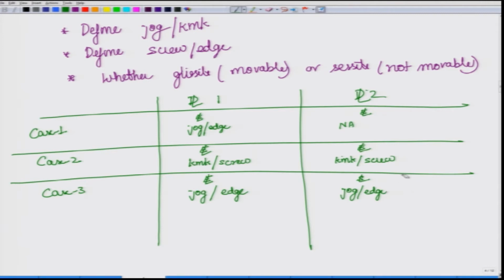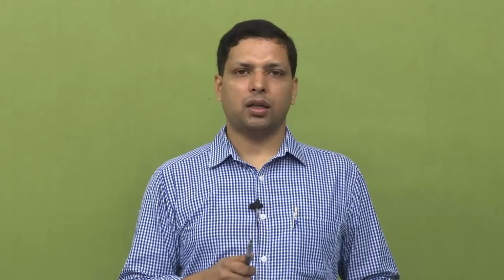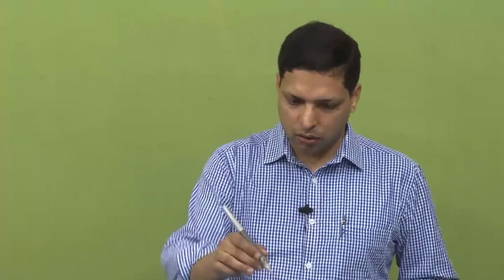So, I will put a star mark over here because this is to be remembered: it depends on which particular slip plane, because there can be several slip planes and just a stationary screw dislocation cannot describe where the slip plane is, while in an edge dislocation even a stationary dislocation can describe what the slip plane is. So, that is why an assumption is necessary about which one you are describing as the slip plane. So, I have put a star mark over here.